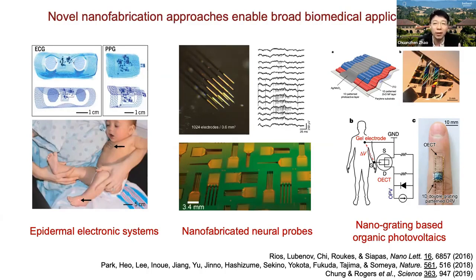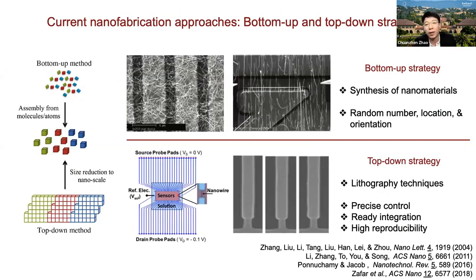Now let's take a step back and take an overview of the general nanofabrication approaches we have. Generally, there are bottom-up and top-down approaches for nanofabrication. The bottom-up approaches generally assemble nanostructures from the molecular level, like growing nanomaterials from their precursors. And the top-down approach, on the other hand, fabricates nanostructures using size reduction from a bulk material, like the commonly used lithography approach. Bottom-up techniques can produce nanomaterials with high quality. However, those strategies have poor control over the orientation of the as-grown nanostructures. As shown in those figures on the top right, the nanowires distribute randomly between those electrodes, and therefore it's very hard to control the reproducibility of the fabricated device.